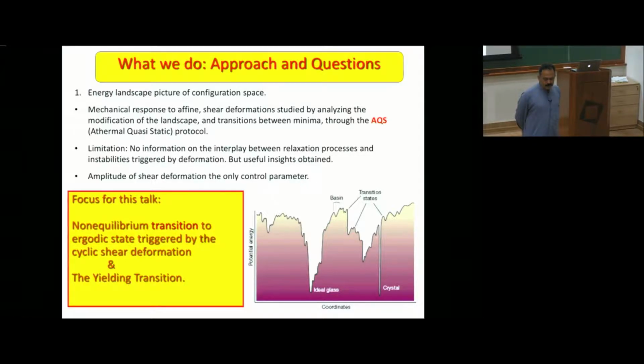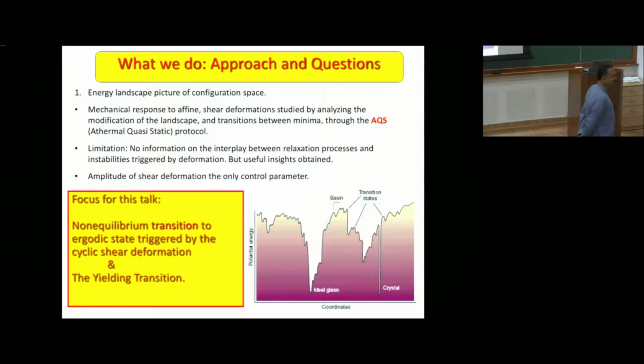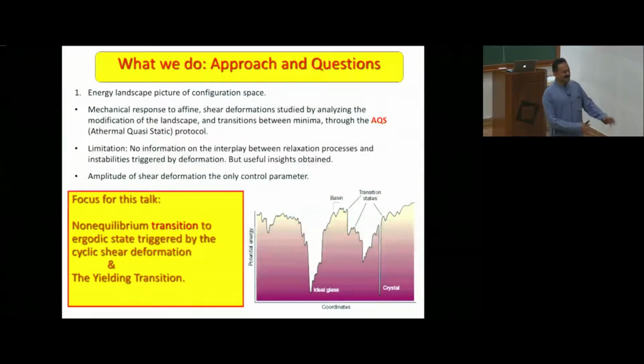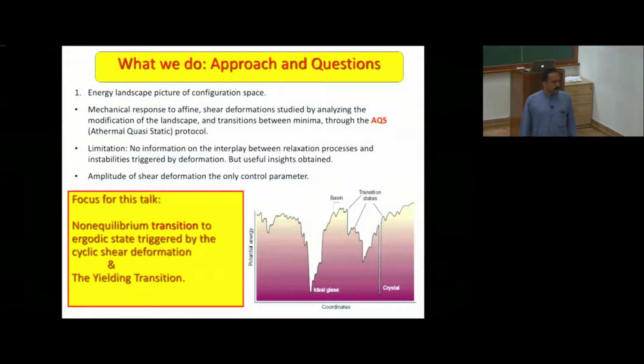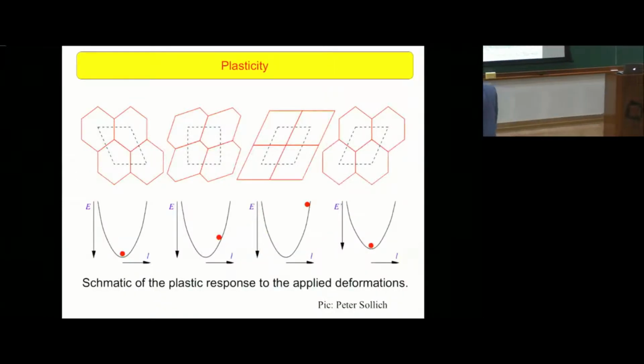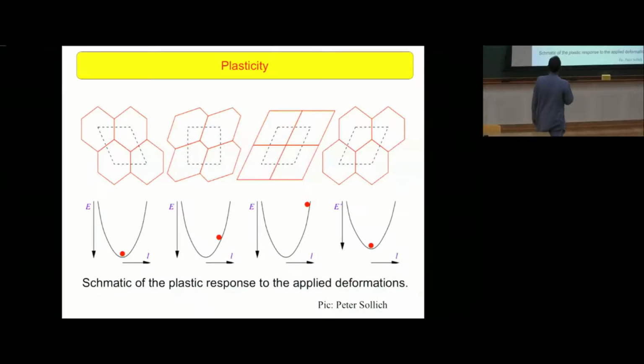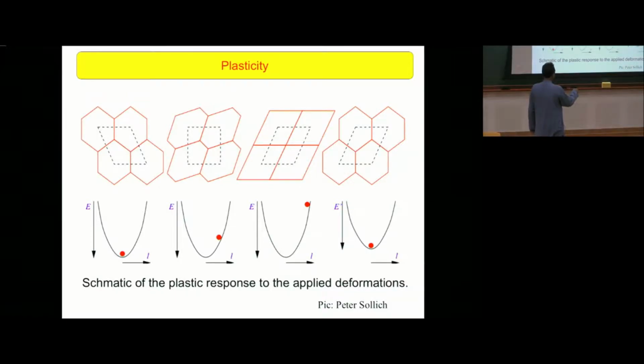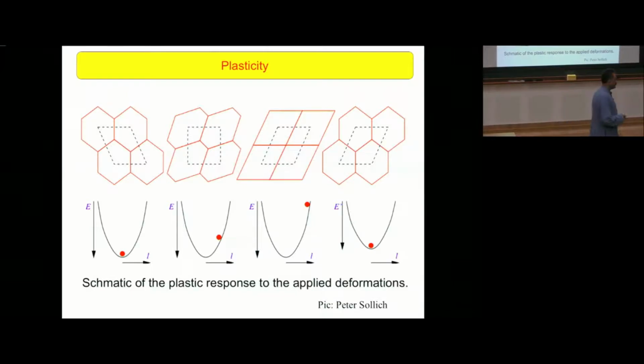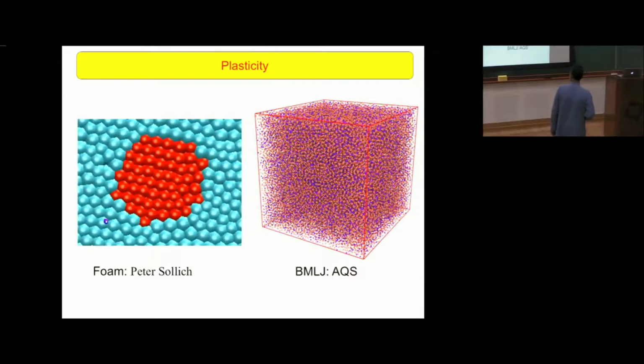And most recently, thanks to a friendly, constructive referee, we have gone beyond this approximation and done simulations at finite rate and finite temperature, and indeed we can see that the behavior doesn't really change. Okay, so this is now a schematic of what you might expect will happen if I take some system which I represent in this abstract fashion, and I'm shearing the system. Eventually it will go to this other state, and if I think of what's happening in the energy landscape, I'm driving the system up the wall till I reach some point which is a limit of stability of that minimum, and then I make a transition to another minimum. This cartoon is basically a summary of a popular model called the soft glassy rheology model, which I'll mention again. And this you already saw, and it's not playing.